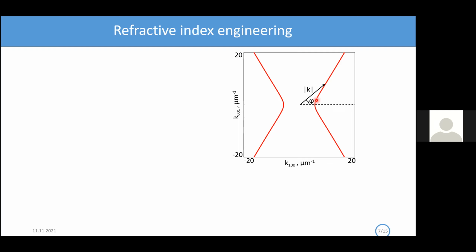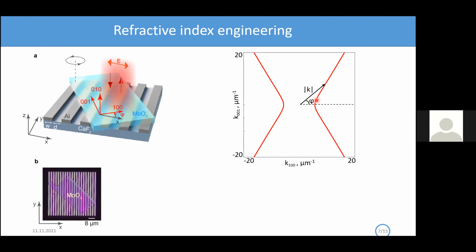Unfortunately, we tried many times to do nanostructuring, but these materials are difficult to structure; they degrade. We use a different approach, achieved by nanostructuring the medium below the flake. To do this, we put our flake on a metal grating.